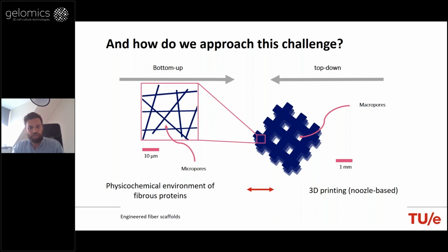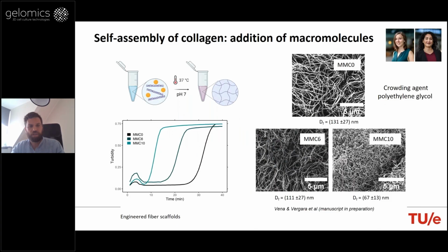We predominantly look at nozzle-based printing techniques like extrusion-based printing and electrowriting, because those, we believe, provide the mechanical environment to confine and organize fiber proteins. And this, we believe, is very similar to what happens in a living cell, because, for example, collagen is secreted by creating invaginations in the cell membrane that create a kind of shear force when laying down the collagen. And then these collagen fibrils, in the presence of other macromolecules in the extracellular space, self-assemble and create large fiber bundles. So one of the areas that we are particularly interested in, as I mentioned, is to understand in which conditions these fibrils assemble.